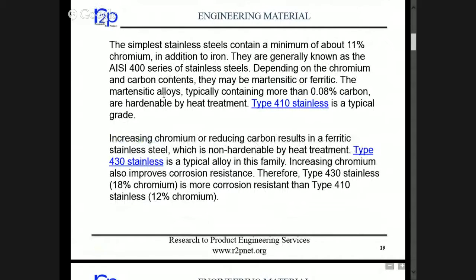So the generally available steel is the AISI 400 series, and the carbon is not much, up to 0.08%, and grade 410 is a very popular grade. We use it in automobiles, and also for general construction or even our household use. 410 is very popular, and depending on the chromium or carbon, it may be martensitic or ferritic. Now increasing chromium or reducing carbon results in a ferritic stainless steel, which is non-hardenable by heat treatment. From 410 we can go to 430.